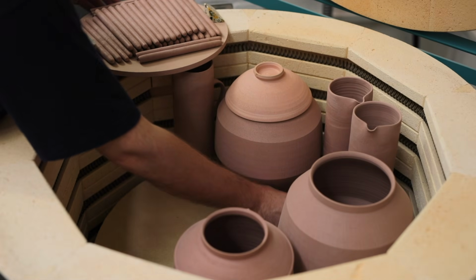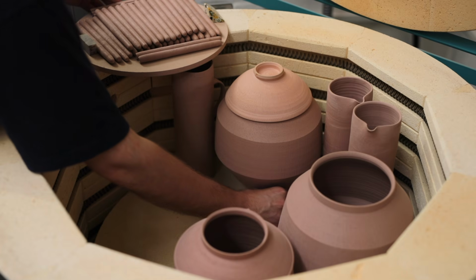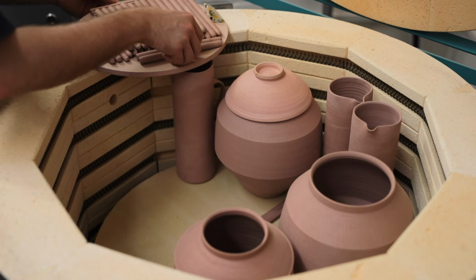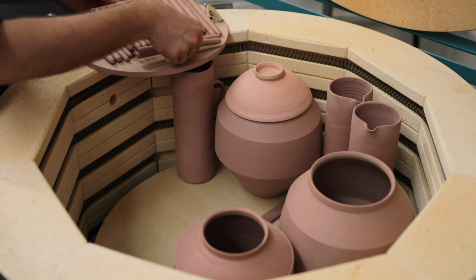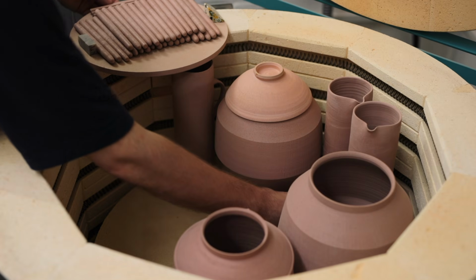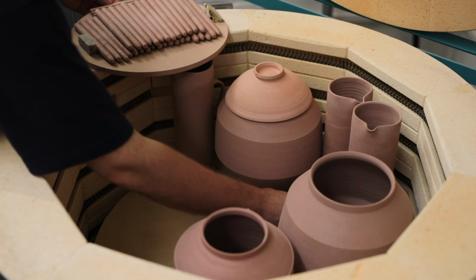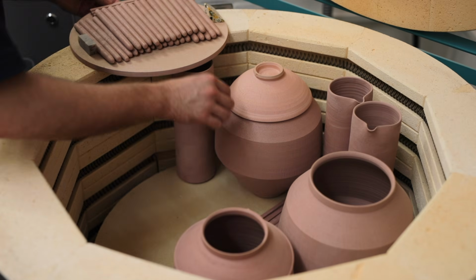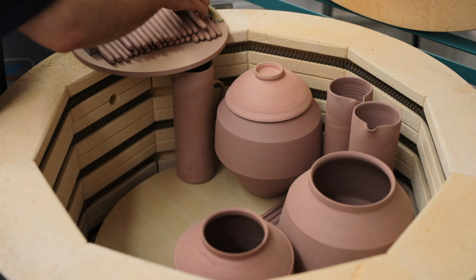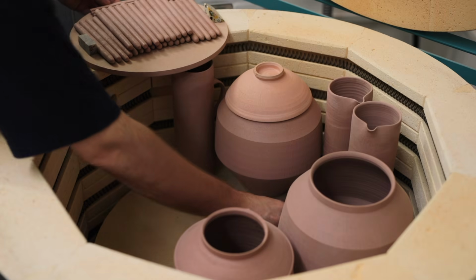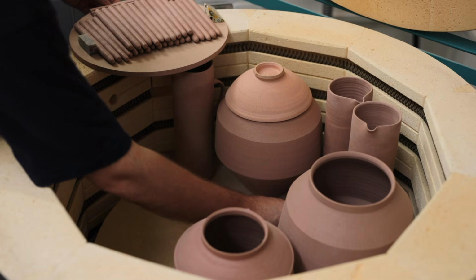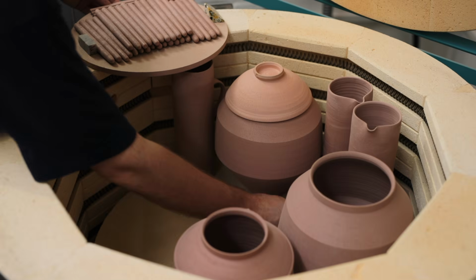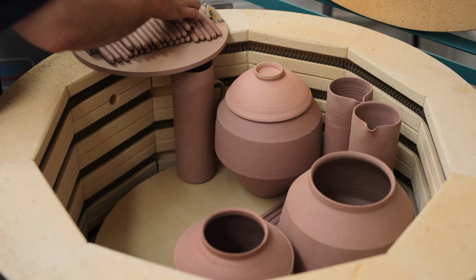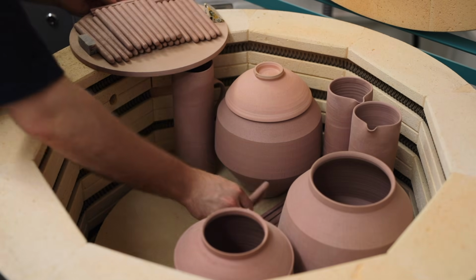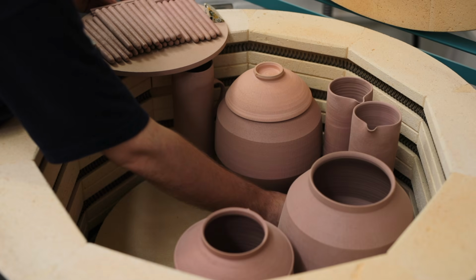But for now, I just pack the kiln as tightly as possible with bone dry pots, making sure that the pen bodies themselves are always laid out to be as flat as they can possibly be inside the kiln. It's at this stage that I've probably had the most disasters when creating these pens, as breaking them at this stage is incredibly easy, as they're so fragile and thin. All it takes is a drop from a centimetre or so, and the length will snap.